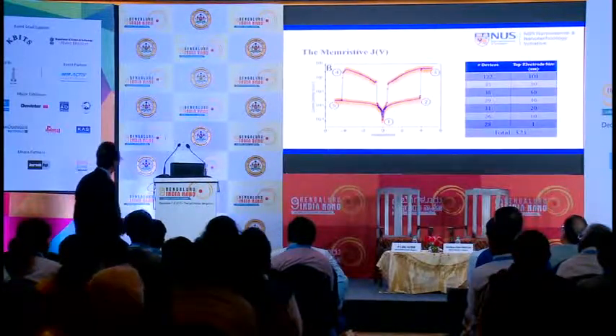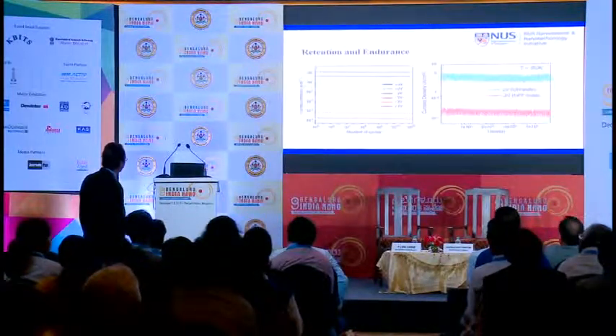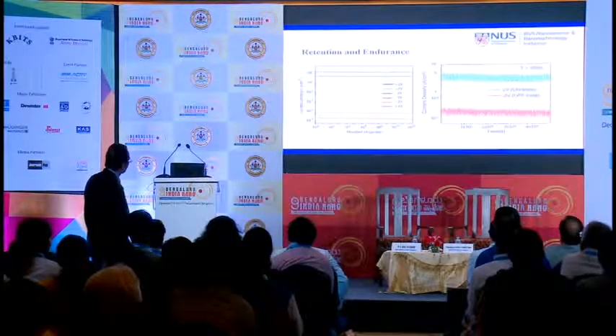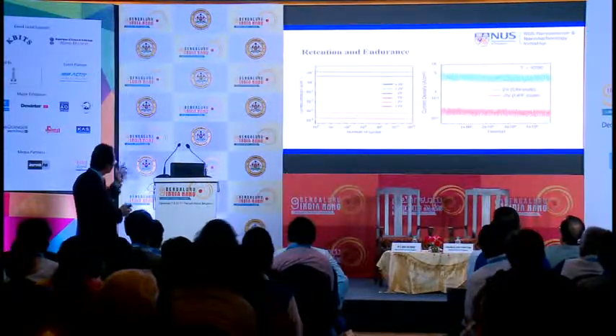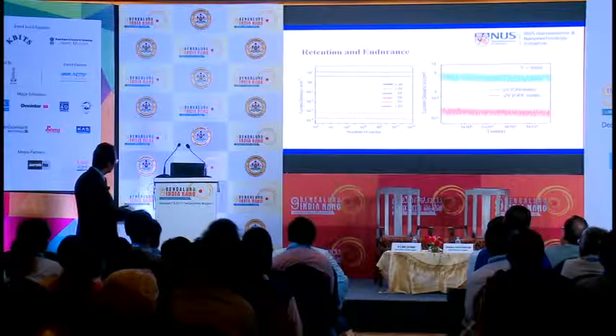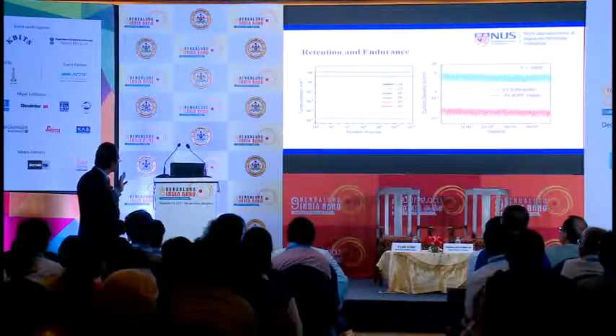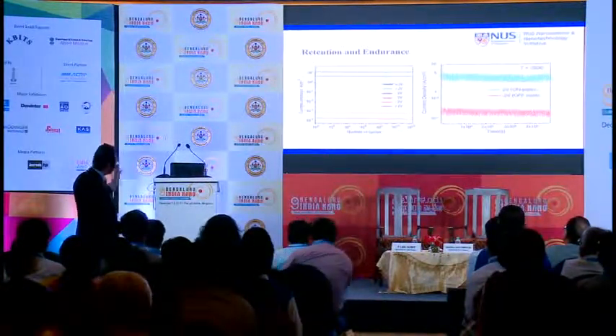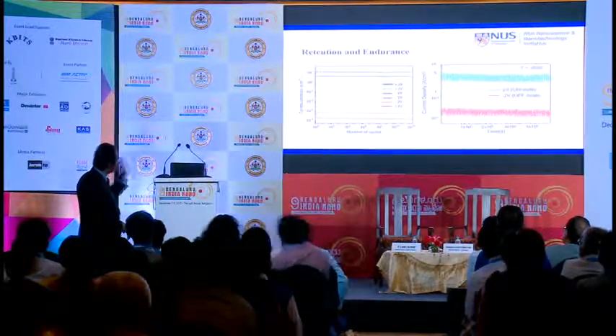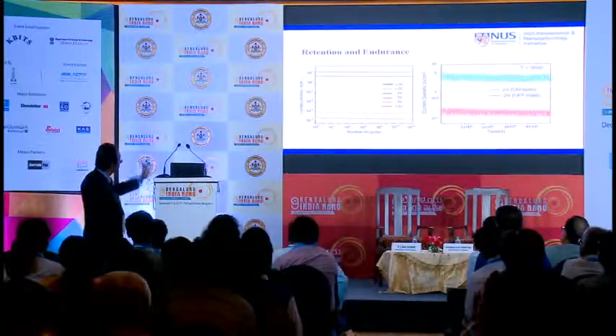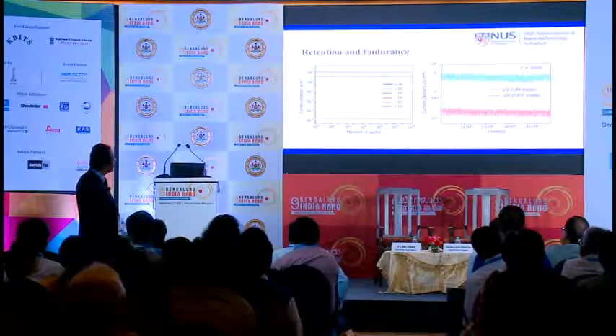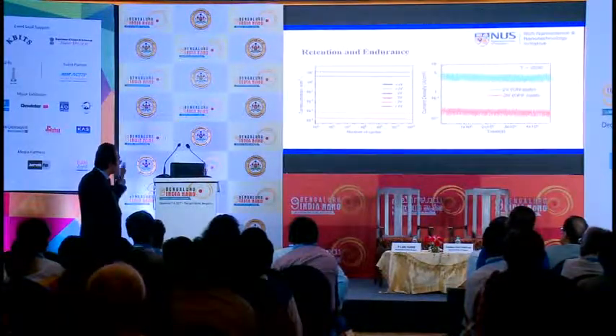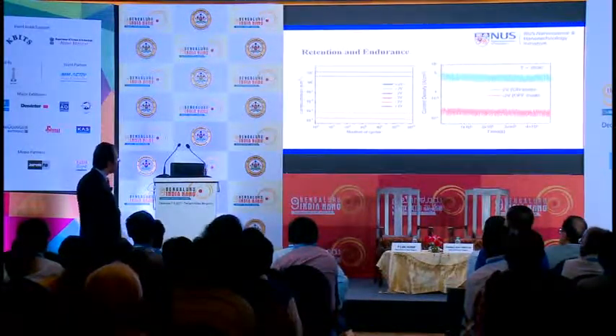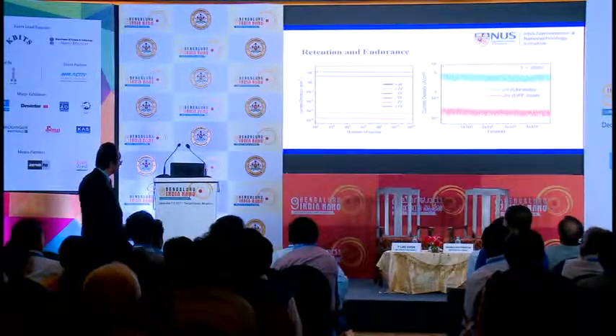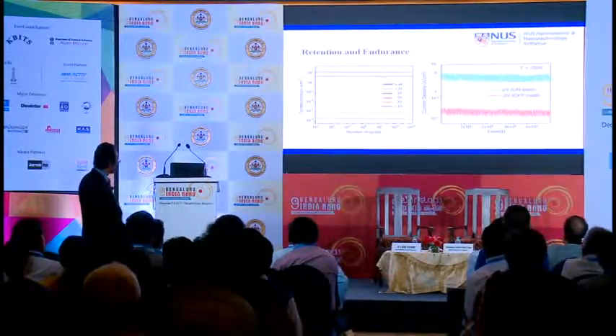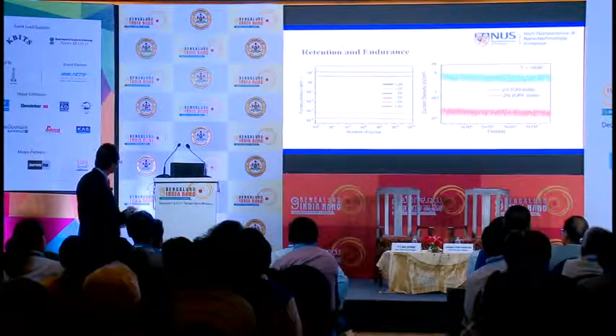Really so reusable. Amazing. Now, you can see, the problem with most organic devices is the number of cycles that you can turn them on and off is very small, typically 10 to the 2 to 10 to the 4 cycles. This device has gone beyond 10 to the 12 cycles and still robust. And it operated at 350 Kelvin, which is almost 80 degrees centigrade, down to minus 30 degrees centigrade without any deterioration at all, which is remarkable, actually.